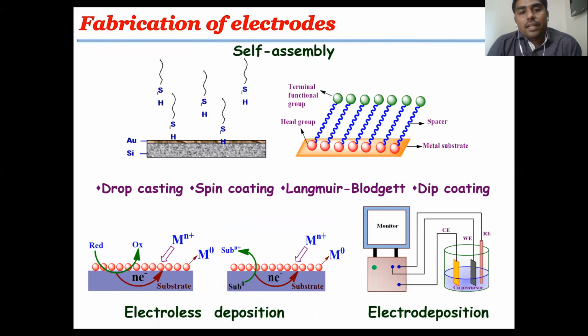Even though the metal nanoparticle composites were synthesized, they must be fabricated on the solid substrate for the nano device, in any form of nano device such as energy devices or sensing devices. Many strategies were followed for the fabrication of the metal nanostructures or nanoparticles on the solid substrate. The first one is self-assembly, drop casting, spin coating, Langmuir-Blodgett, dip coating, electroless deposition, and electrodeposition.